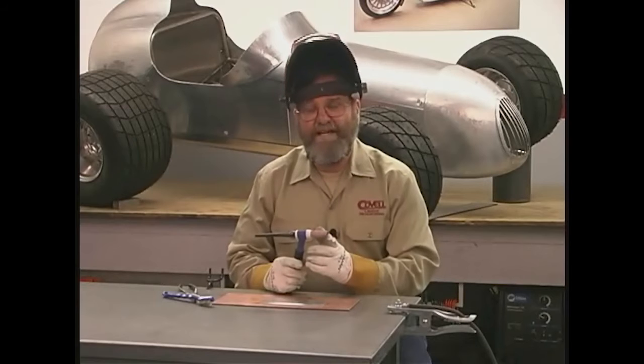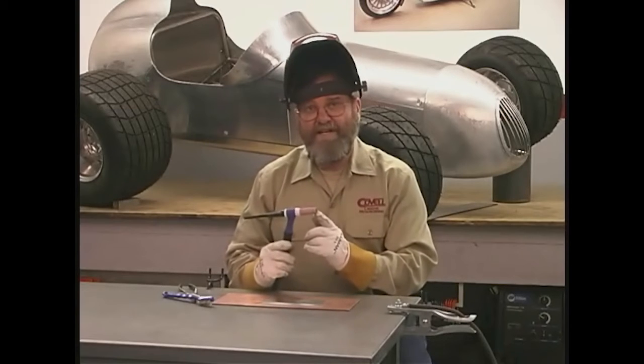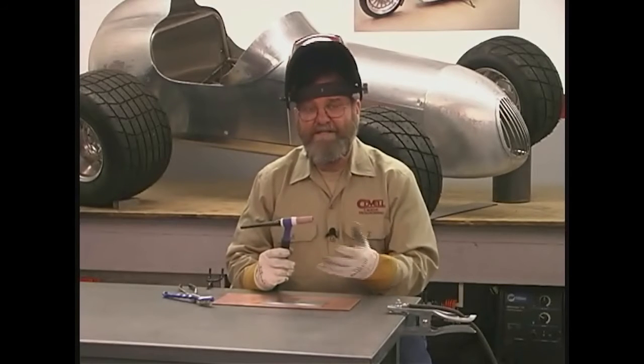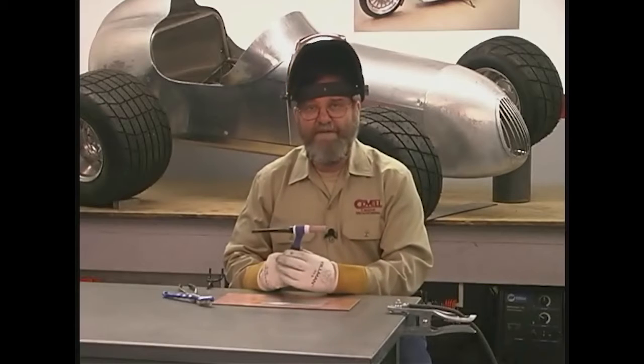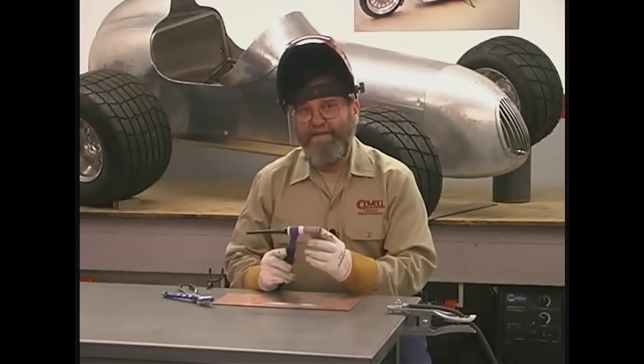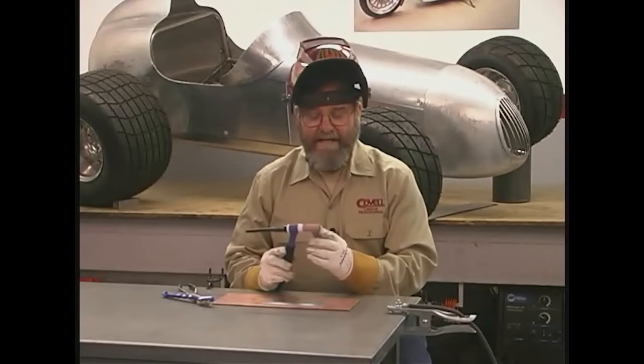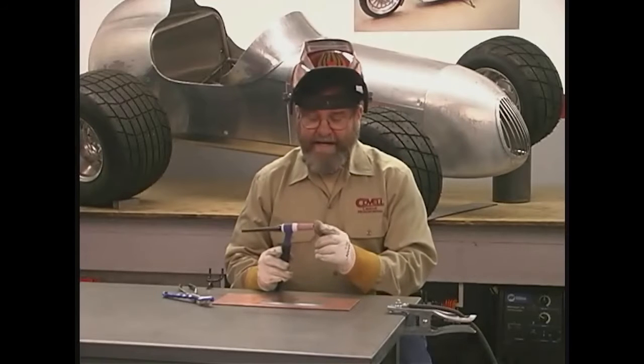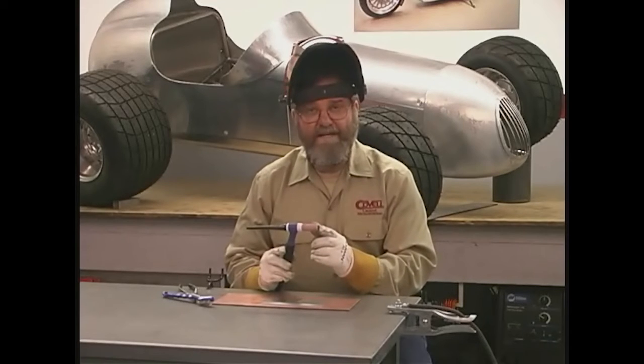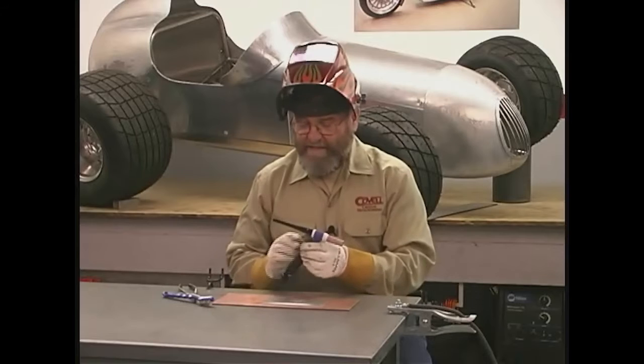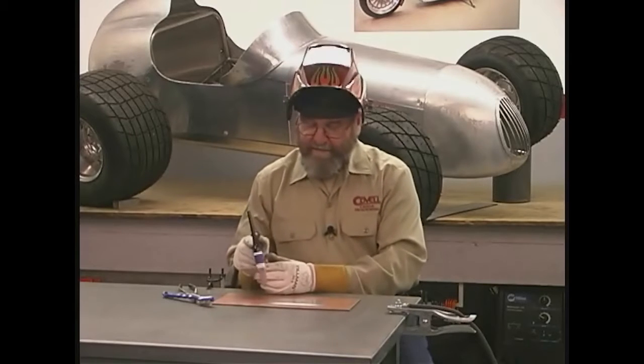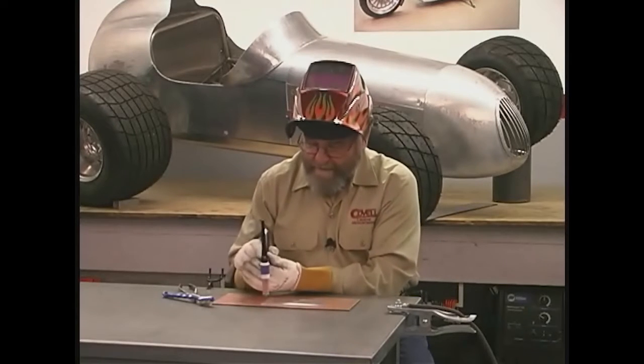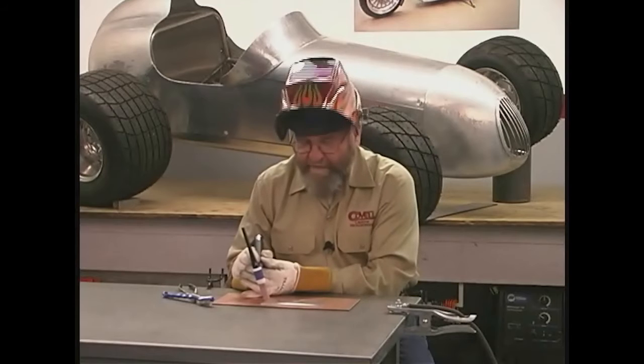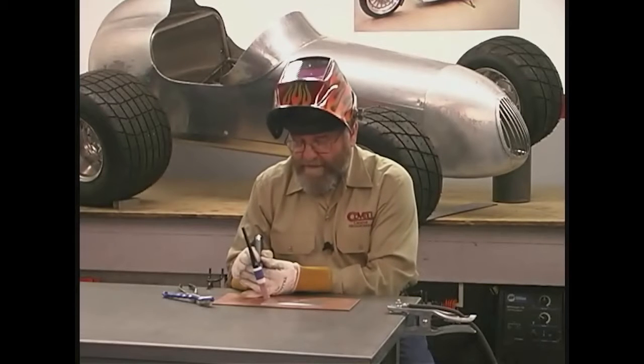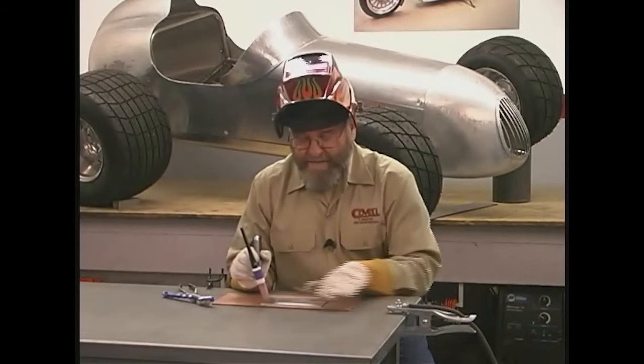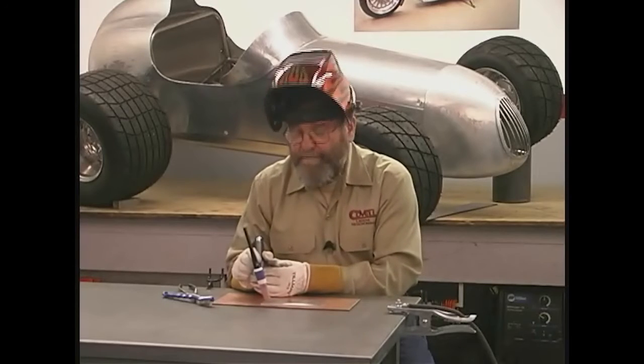of post-flow set. I've gone to a larger tungsten. We need to have larger tungsten because we're flowing more current for the aluminum. So it's a 3/32 diameter tungsten, it's 2% ceriated, and it's sharpened to a very fine point. So just like we did with the steel, we're going to get some pre-flow going by bumping the pedal. Then I'll hold the torch at about a 15-degree angle off the vertical, start the pedal, and just move it slowly across the panel.